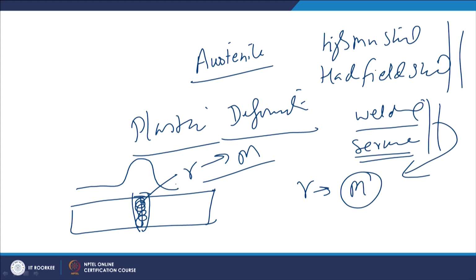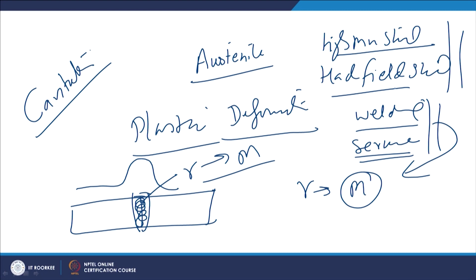So, here the plastic deformation is important, and such steels are found very suitable for applications where cavitation is involved, like in fluid flow systems where cavitation is causing loss of material. Cavitation develops the impact of high pressure waves onto the steel, leading to controlled surface layer deformation, and the surface deformation associated with the austenite to martensite transformation increases the hardness, and thereby helps in reducing the erosion of the material.